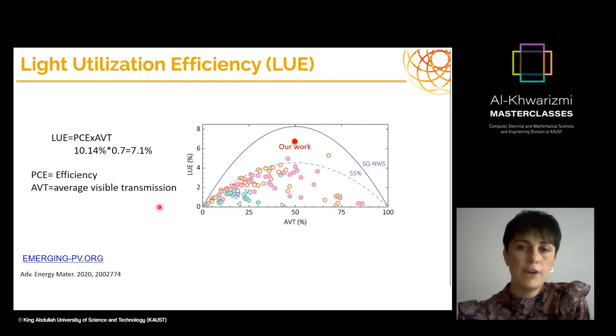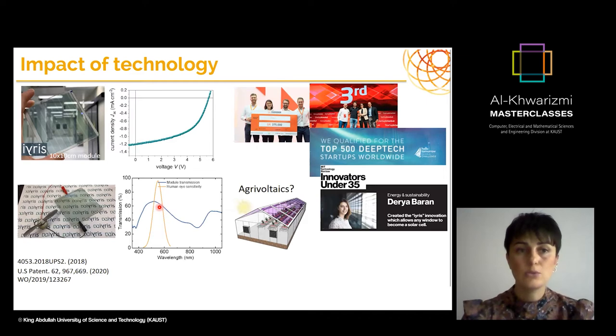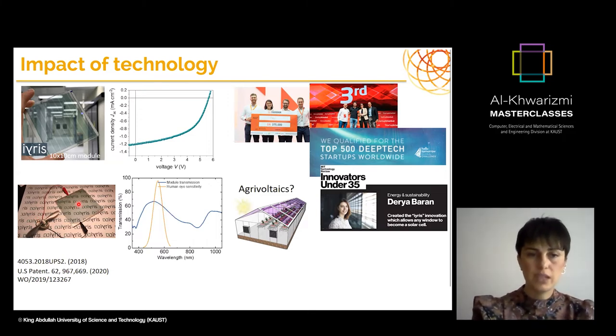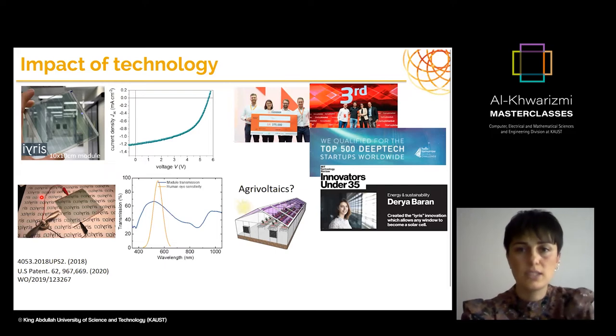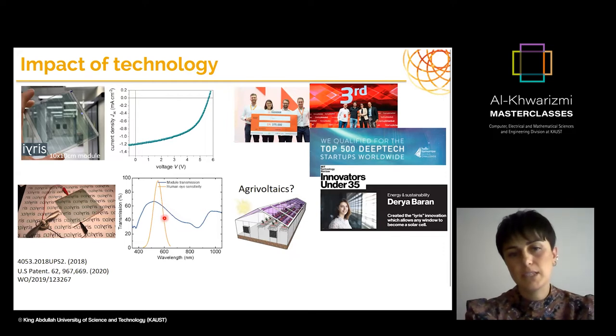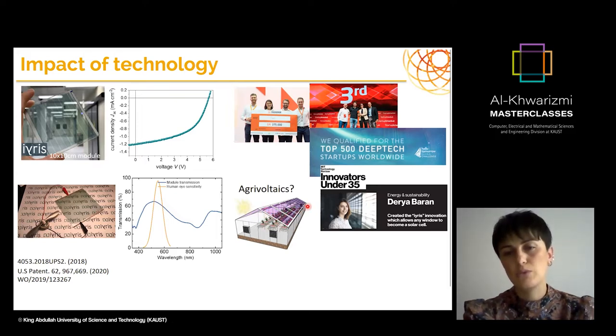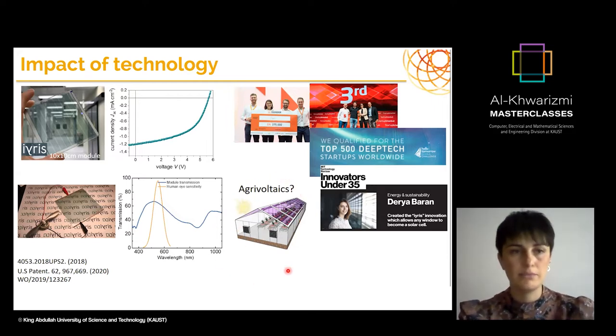So these initial findings really inspired us at the time. And what we did was, at KAUST, we had a startup to go for transparent photovoltaics. And here you see one of our modules that works, 5 by 5 centimeter. And we had won several startup awards, etc. Our vision at that time was to use these semi-transparent devices for agrivoltaics, because this particular combination is highly transparent, where not only human eye sensitivity is very high, but also where plants need to grow. So if you use this combination, you can keep the parts that are required for the plants, but absorb the further infrared light and use it for energy conversion while your plants can still grow happily. So this is now taken as a startup and moving on its own way.